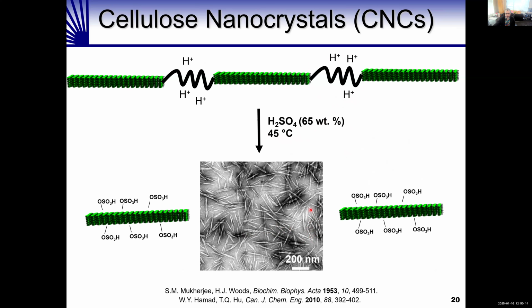An important part of this process is that the cellulose nanocrystals get coated with sulfate groups, which give them a surface charge and allow them to form stable colloids in water.